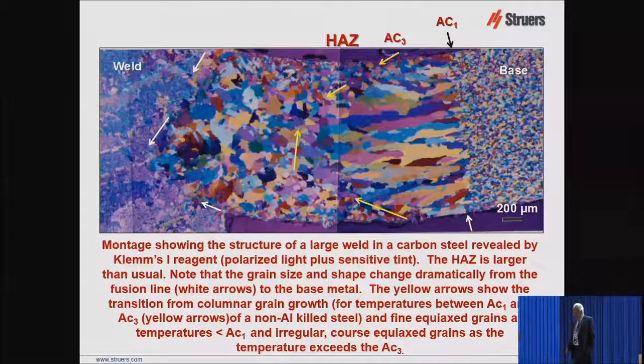And you can see once we're past the Ac3, the grain structure is getting coarser and a bit more irregular in shape. And our fusion line is quite easily visible in color, and the weld metal is showing up beautifully. That is infinitely better than the original structure in Nital.